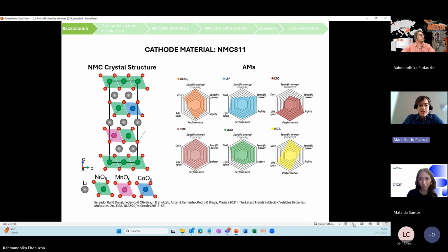NMC is an interesting material. It has a layered structure, formed by a layer of lithium atoms and a layer of transition metal atoms in a hexagonal pattern, and these are coordinated in an octahedral configuration. In this case, the NMC 811 material has in its transition metal layer 8 atoms of nickel for each 1 atom of manganese and cobalt, but there are other NMC materials. However, NMC 811 is interesting due to its high specific energy, which theoretically should be around 275. Experimentally, you should get around 180 to 200 milliampere hours per gram.